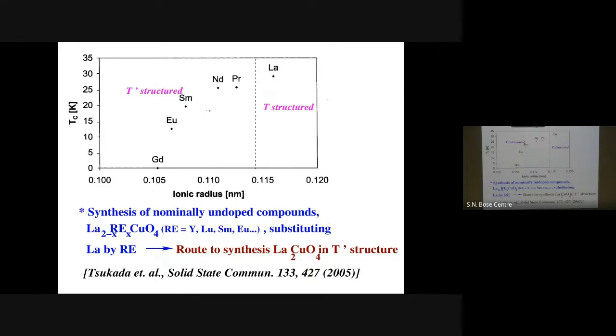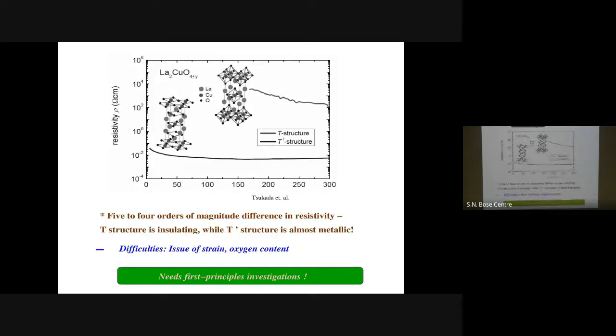So what these experimentalists did is replace a part of lanthanum by some of these, and by that, even the pure La2CuO4 they could stabilize in T prime structure. So they considered that as a route to synthesize La2CuO4 in T prime structure. Well, the surprise came when they measured the resistivity. They found the resistivity in the T structure is four to five orders of magnitude larger than that of the T prime structure. And looking at the temperature dependence of the resistivity, while the T structure is clearly insulating, the T prime structure is almost metallic. So what causes this big difference?